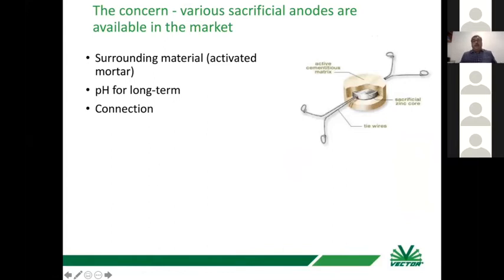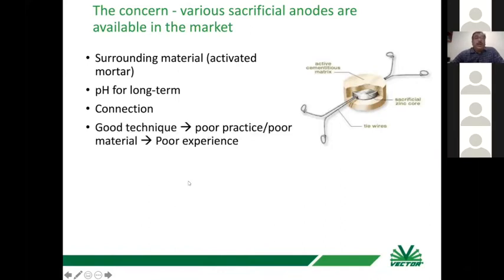But how to select the anode? Your anode has to properly have an activating mortar which should keep zinc corroding. It should have an alkali material. It should not have halides or salts, and it should keep zinc corroding for 25 years so that the pH for long-term connection is maintained, so that when zinc is corroding, you have a connection of rebar and the zinc for 25 years. It should not be welded. It should be cast inside the zinc anode. If you have welding or screwing of the wires at the zinc, when zinc is consumed, this connection will go off and the anode will not be usable. So this is a wonderful technique, but poor practice or poor material will give you a poor experience and the whole technology will die.